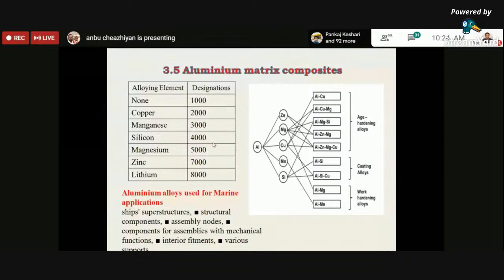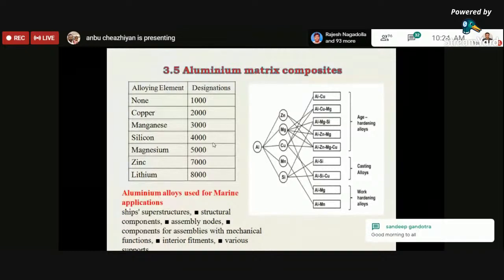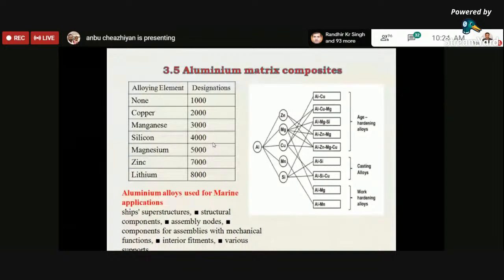So there is a major drawback in aluminum. At aging temperature, the coherency between the precipitate and matrix lattice disappears due to the growth of reinforcing precipitates, and hence it loses the hardening effect. As a consequence, the strength of the alloys decreases. They mostly go for 200 to 300 degrees centigrade. In that case, the inclusion of ceramic reinforcement tends to increase such properties.